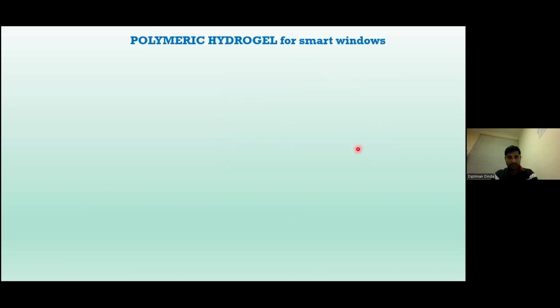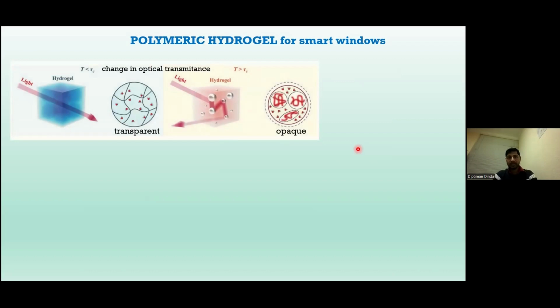Now the polymeric hydrogels. Polymeric hydrogels change their optical transmittance when they are exposed to heat. In case of cool weather, they are dispersed in the water medium, so they behave as a transparent medium to pass through the light. But when we heat these polymeric hydrogels, then because of the phase segregation, they will agglomerate, and now they will scatter light. As a result, their transmittance will change, and they will become opaque, and they will block the light from passing through the medium. So depending on the opacity of the medium, they will block the light. And that's how they work in smart windows.